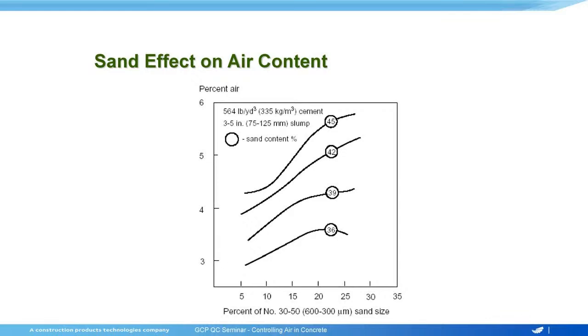But again, if you're struggling to get air, if you can put a little more sand in the mix, and we see this not just in precast, but in ready mix as well, especially with higher strength mixes, sand content tends to be low. We bump the sand a little bit. We make that adjustment, and we see that we can get air much easier and much more consistently.